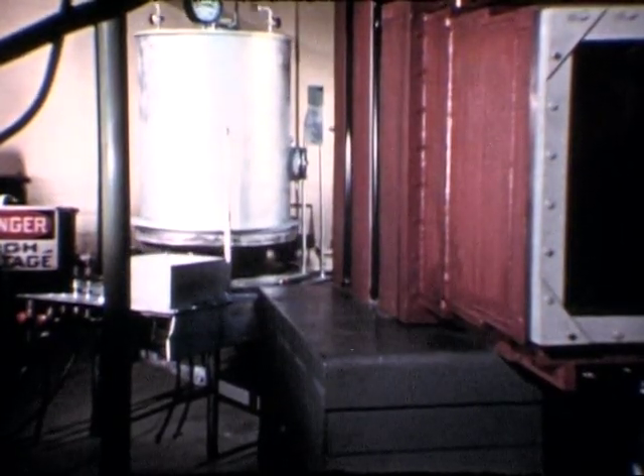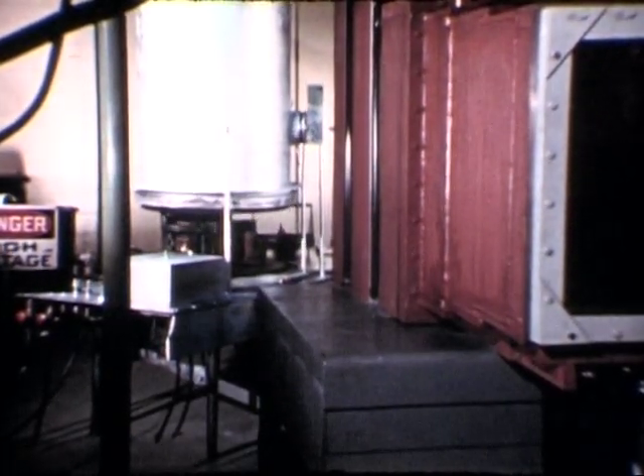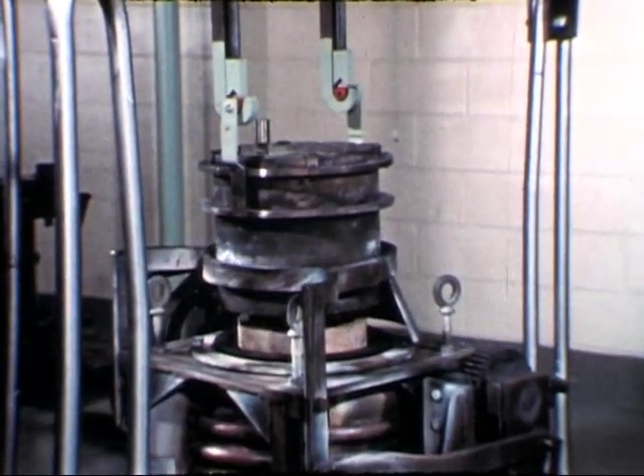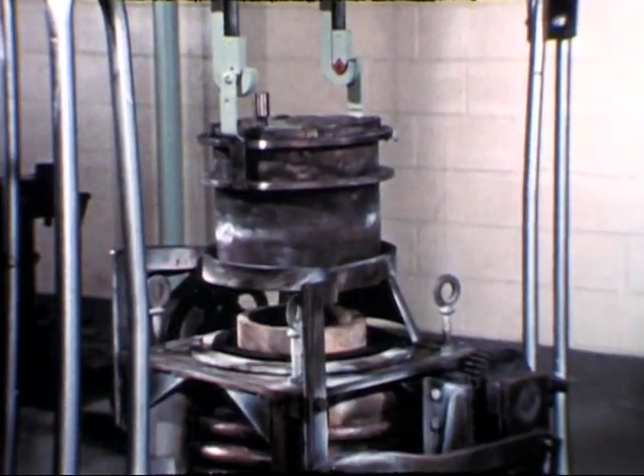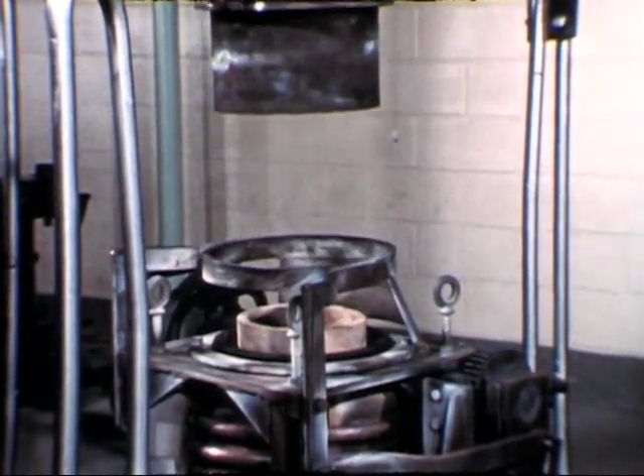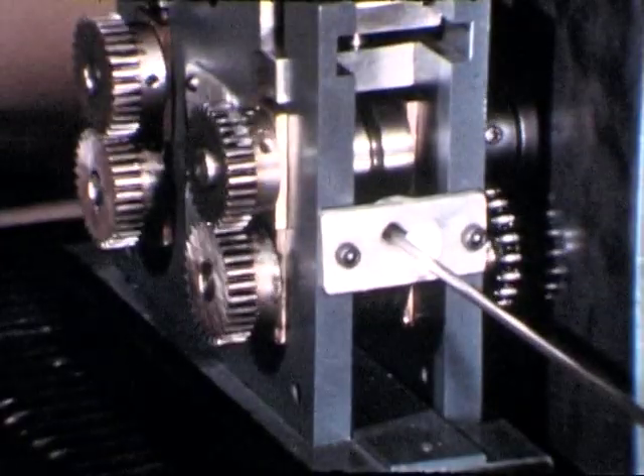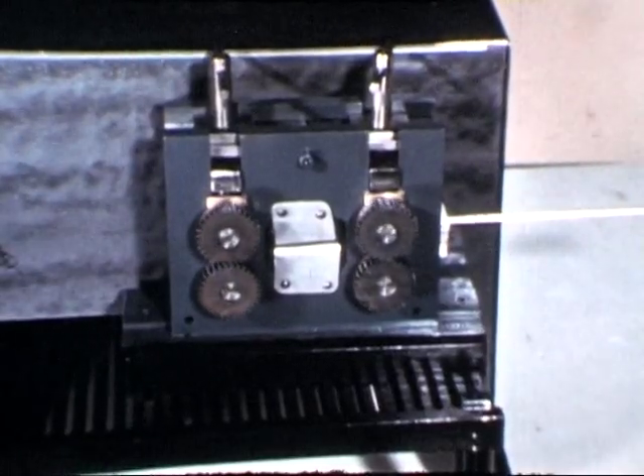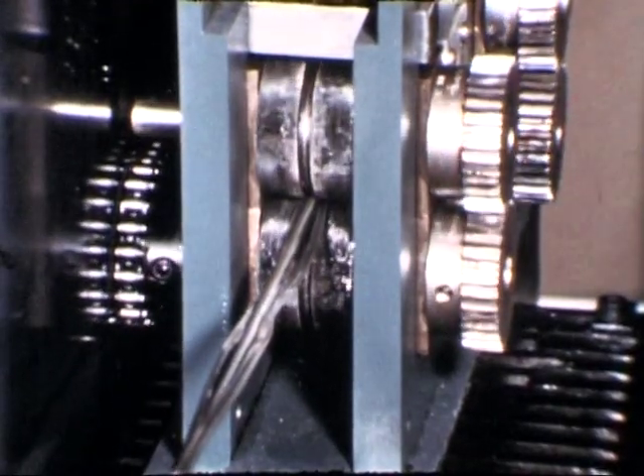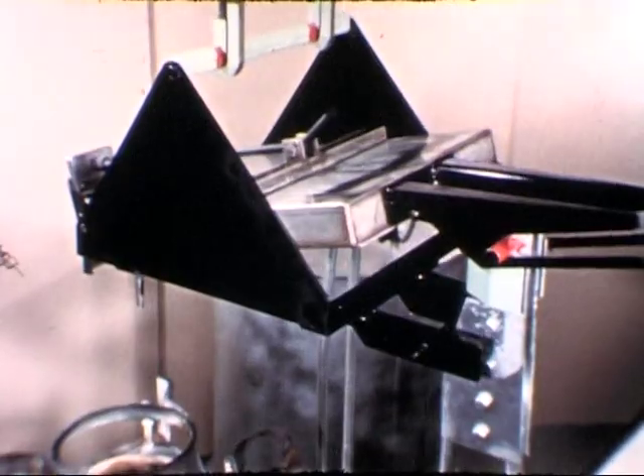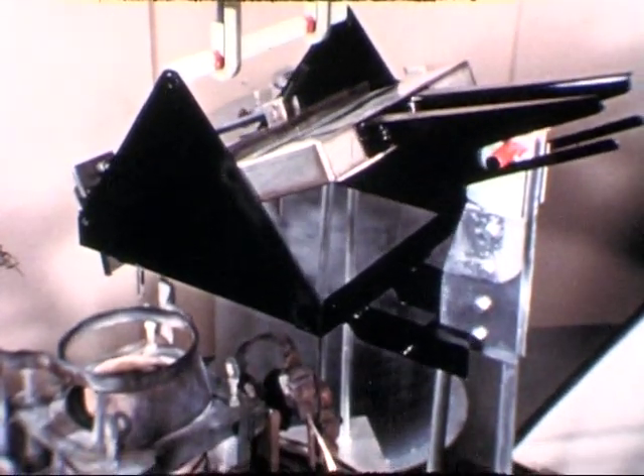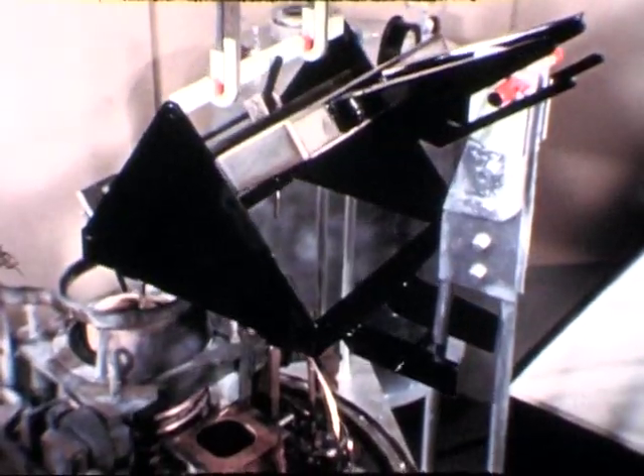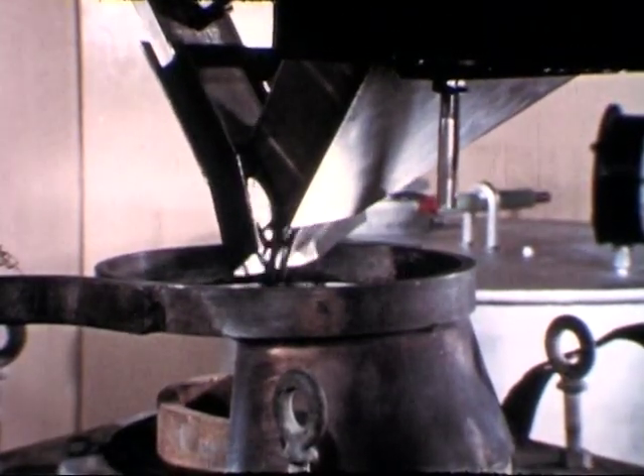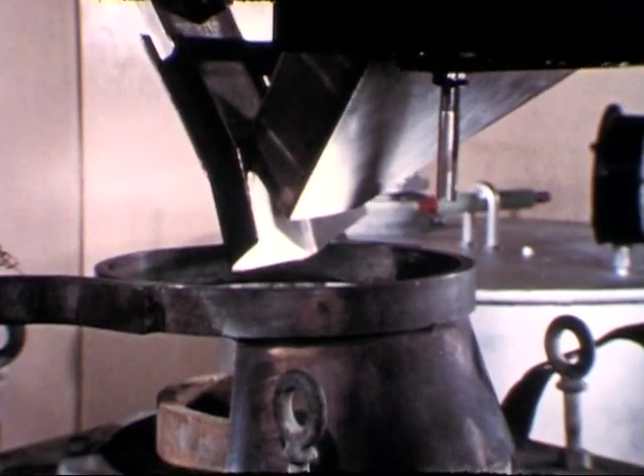The process sequence begins. The melt refining furnace is enclosed with a bell jar to provide a furnace environment independent of the cell atmosphere. A fume trap to collect volatile fission products is removed. Prior to charging, the fuel pin is mechanically separated from the stainless steel cans and chopped to a pouring length. Due to the self-heating of the radioactive fuel, special containers like the fuel charger must be enclosed and designed for heat dissipation. 10 kilograms of chopped fuel pins are charged to the furnace crucible.